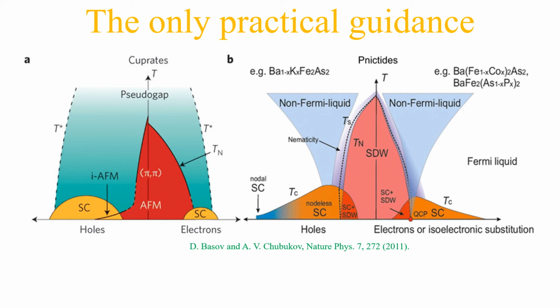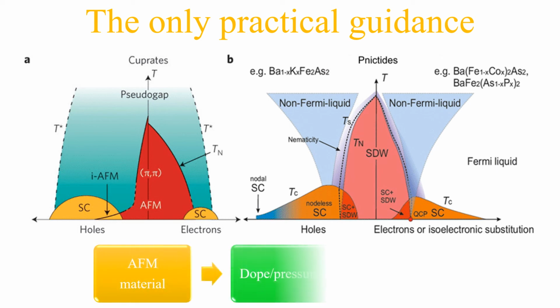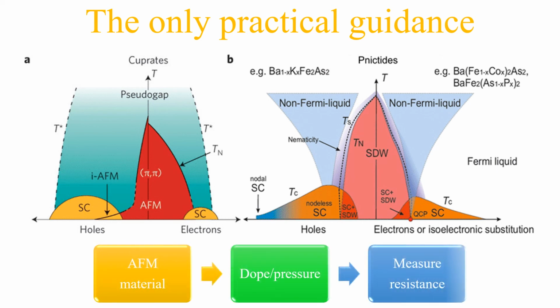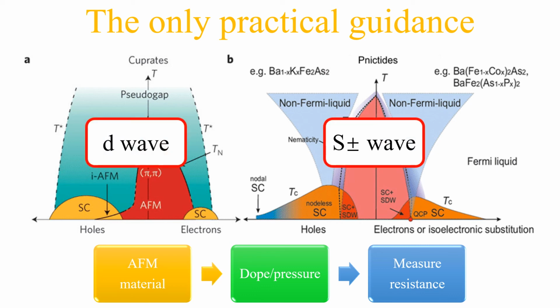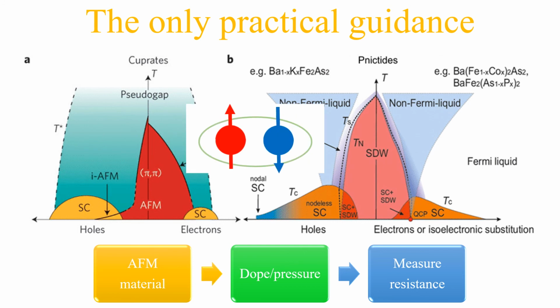So a lot of people are working along this line. Take an antiferromagnetic compound, apply pressure or do chemical substitution in order to suppress the antiferromagnetism, then measure resistance to see if it superconducts. If not, try another one. However, this is not going to help us find a triplet pairing. We know the cuprate is d-wave and iron-based is s-wave. Both have spin singlet pairing.